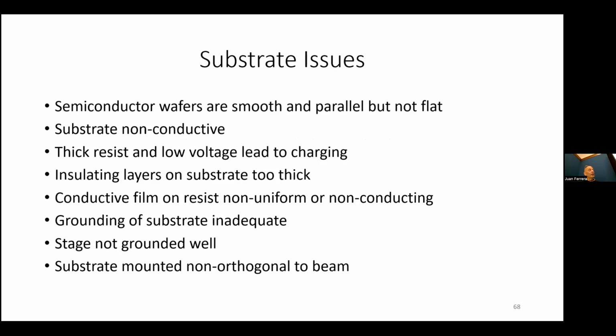Yeah. There also could be substrate issues. Semiconductor wafers are just beautifully flat and smooth, right? Well, they actually, and they're parallel. They're smooth, but they're not really flat in that they'll often have a spherical distortion. So like a 4-inch wafer might be 40 microns higher in the center than at the edges unless you have some good clamping system. But I point this out because if somebody brings in a glass slide or maybe a piece of tungsten that they've had machined, it will not be smooth, it will not be flat, it will not be parallel, and these will all be issues.